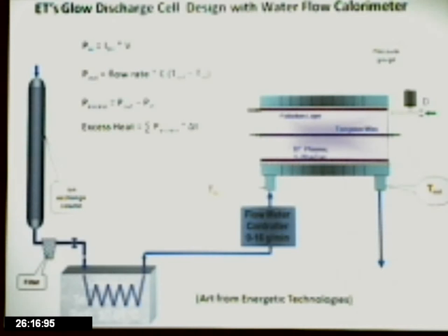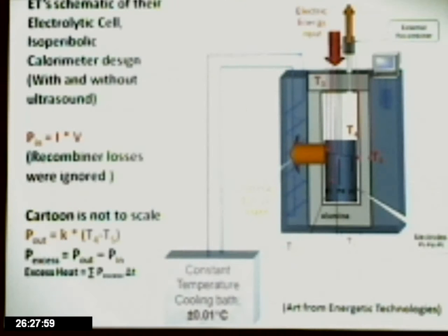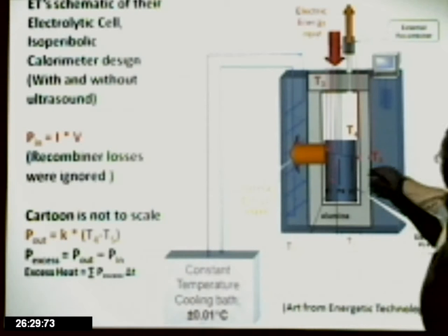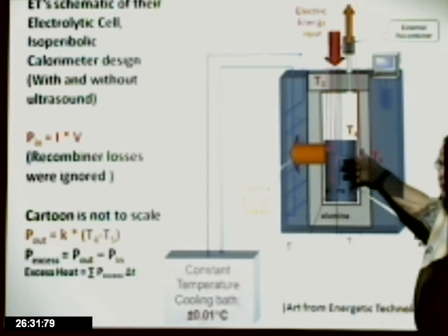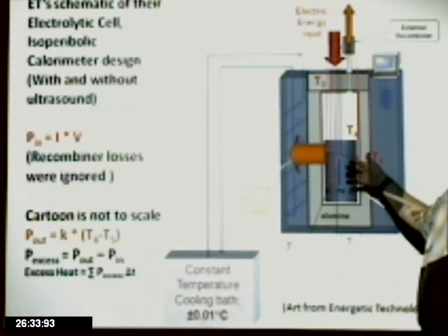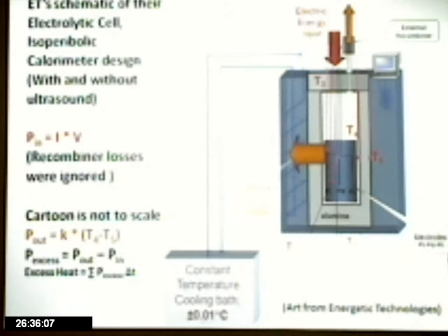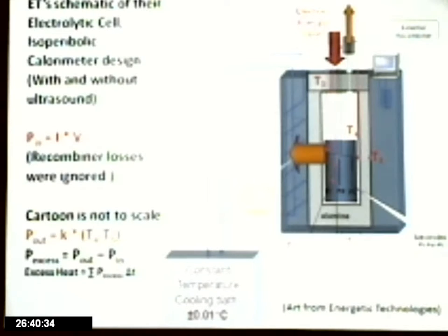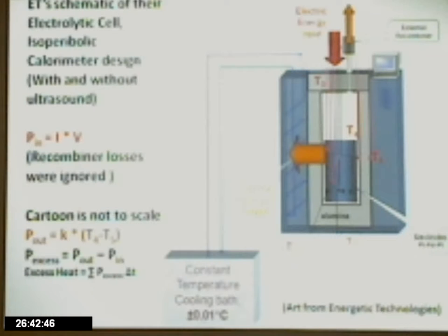The other interesting thing about this is that I said there were 3 different techniques. This is one you saw before. The other technique is a variation of what we saw the first time. It's using this, but doing it in the field of very intense ultrasound. Doing the electrochemical loading in intense ultrasound, where the ultrasound ravages the surface. And in those cases, they saw excess heat about 70–80% of the time.